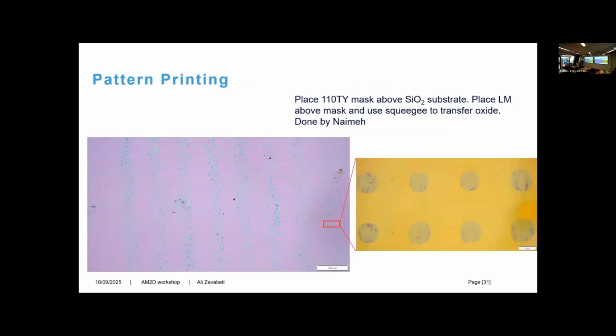We can show printed shapes. And this is done through a mesh. What Naimeh did was basically put a mask above SiO2 and then push liquid metal through it using a squeegee. And we could get these very nice arrays that we have not done before using liquid metal technology. We don't have any direct lithography methods. We still can do lithography, but using maybe photolithography or other types of lithography, or maybe electron lithography. But using direct printing, we haven't done it yet, so this is the first time.